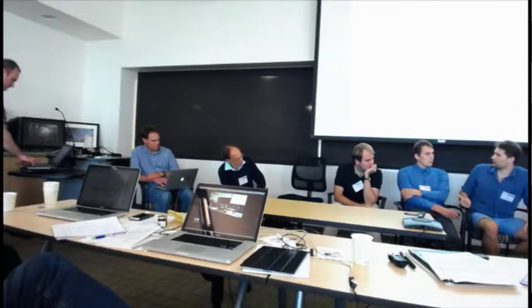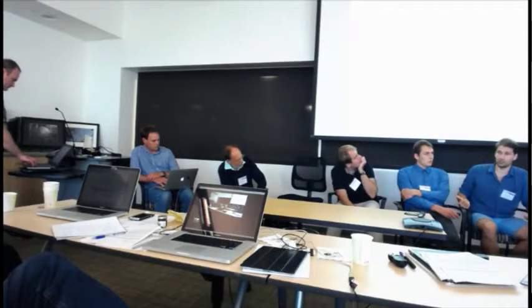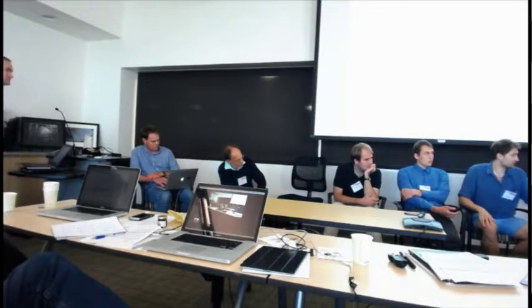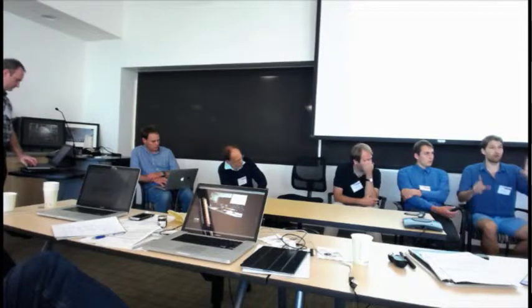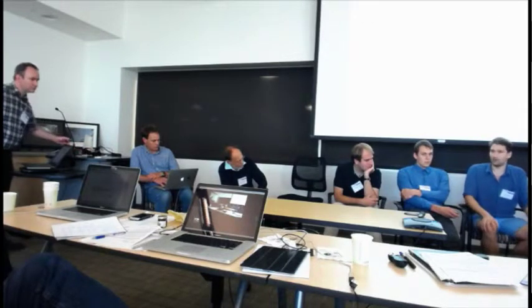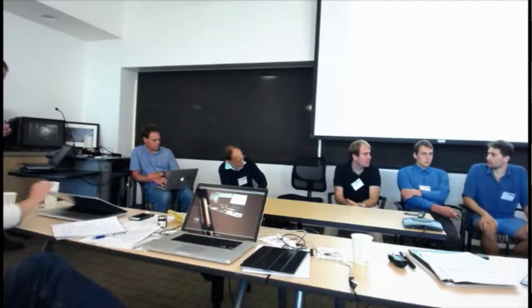It sounds like what Wolfgang mentioned at the end of his talk is that if you try and apply those kinds of things, you get worse results than just taking the raw partial intensities. And that's also been our experience. A reason why that could be is that the initial accuracies of these orientation things are such that your first guess corrections are worse than your partial intensities. I was wondering if that was the experience across the board, and what people thought of that.